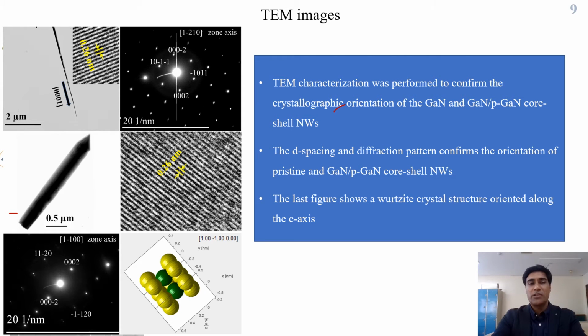And similarly, from the diffraction patterns of the pristine and the GaN/p-GaN coaxial nanowires, we can see the nanowires are grown along the c-axis. Their crystallographic orientation is c-axis, which was confirmed from the d-spacing and from the diffraction pattern. And the last figure shows the wurtzite crystal structure, which is oriented along the c-axis. It was generated from software.